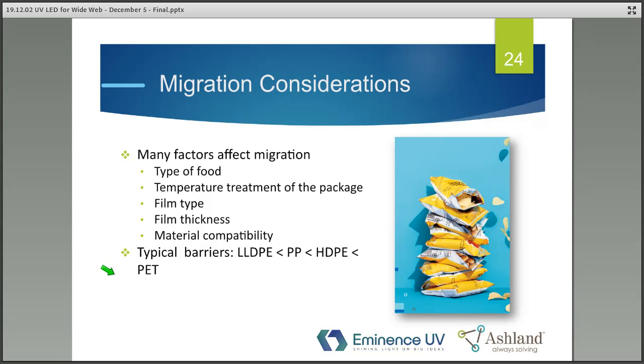If you look at barrier films, generally linear low density polyethylene is a screen door to migration. It's probably one of the worst ones. We use it at Ashland as a worst case screen method, followed by polypropylene, high density polyethylene, and PET.